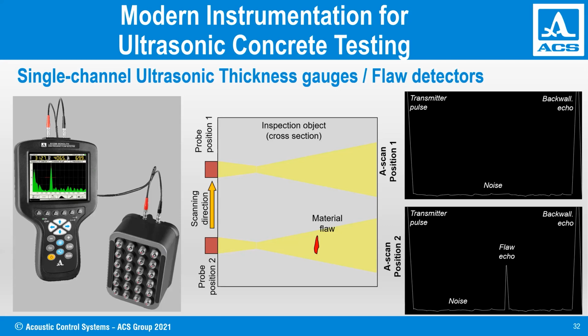If the backwall signal is sometimes disappearing, that means something might be inside. This is the so-called shadow method, where by collecting the data over the surface we just look at the positions where the backwall has disappeared, which might be the indication of some defect. Or, if there is some delamination inside, our backwall signal will be in the wrong position, not in the full depth, but somewhere in between.